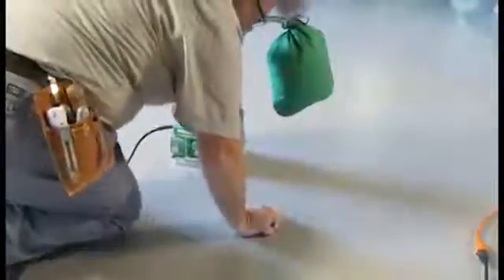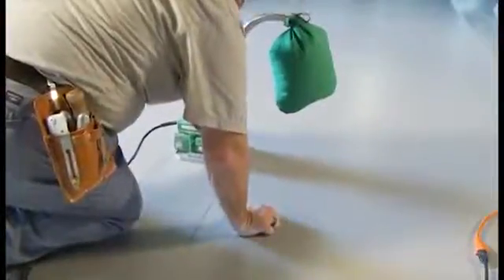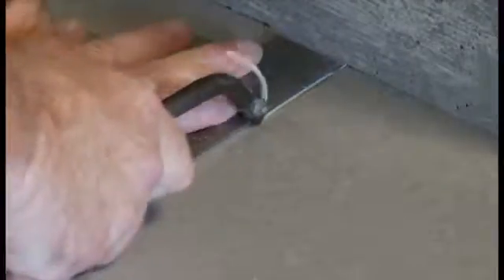Router groove the seam to 2/3 the depth of the vinyl. Use an electric router equipped with a 3.5 millimeter thick blade. In areas where an electric router cannot be used, use a hand router. The routed seam should be free of dirt, adhesive, and particles produced by routing.